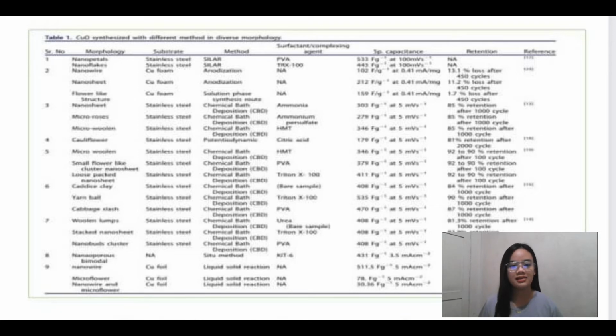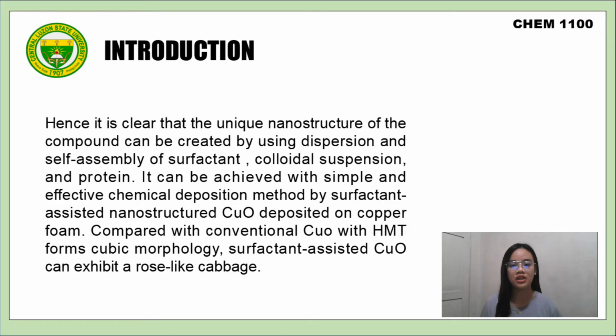Table 1 explains synthesis of copper oxide in diverse morphology using different methodology and their performance at a glance. In this work, surfactant-assisted nanostructured copper oxide was deposited on copper foam by a simple and effective chemical deposition method. Compared with conventional copper oxide with HMT, which forms cubic morphology, surfactant-assisted CuO exhibited a cabbage rose-like structure. The specific capacitance obtained for surfactant-assisted CuO was high, with excellent cycle stability.